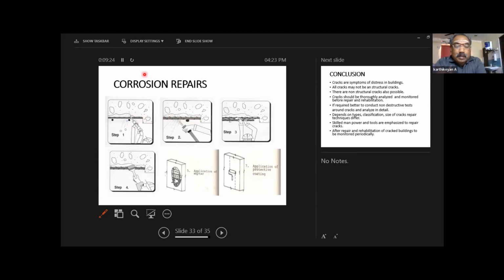When you remove it, definitely the diameter may get reduced. A 16 mm rod may become 12 mm or 10 mm. You have to use a vernier caliper. What is the original diameter of the rod and what is the diameter after removal of the corrosion? If the corrosion loss is more than 20%, then you have to weld additional rod. Otherwise, you can proceed.